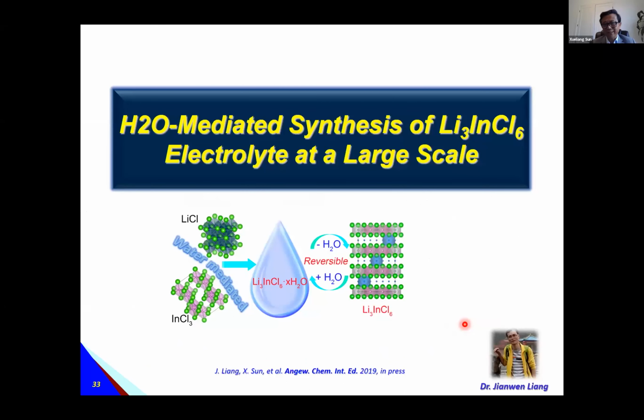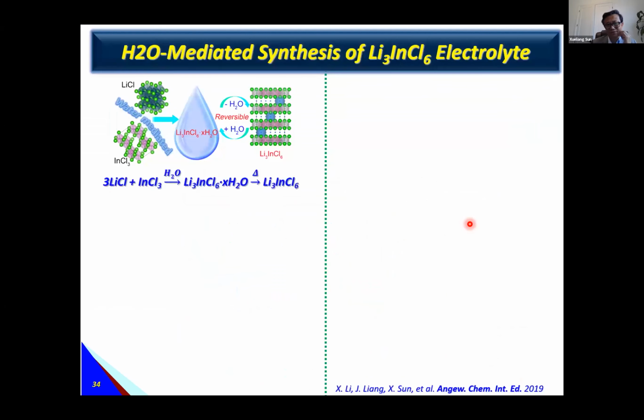So after this study, we looked at how to scale up mass production of this material, lithium indium chloride. We developed a solution method. We're just using lithium chloride with indium chloride.